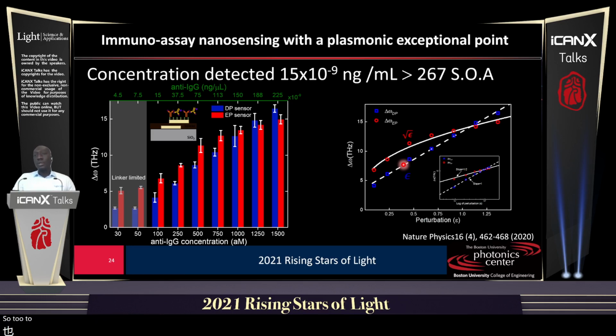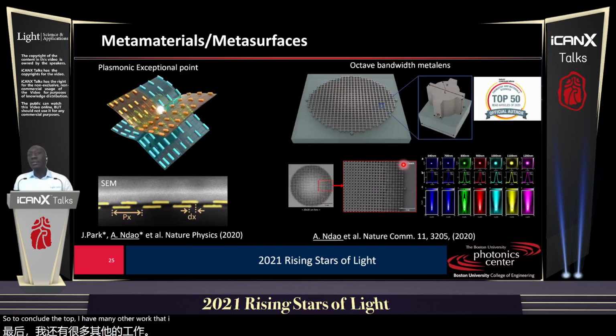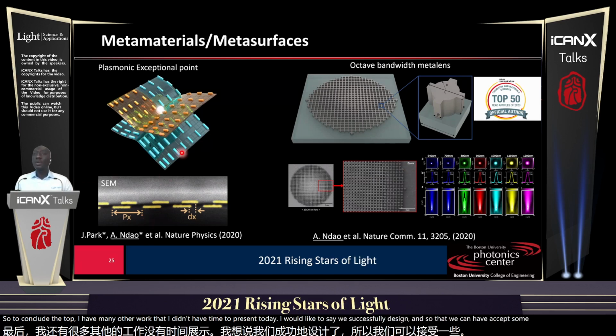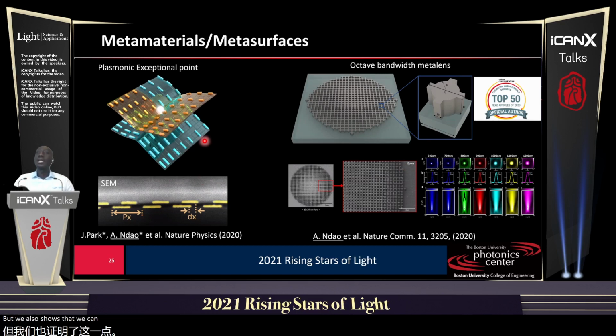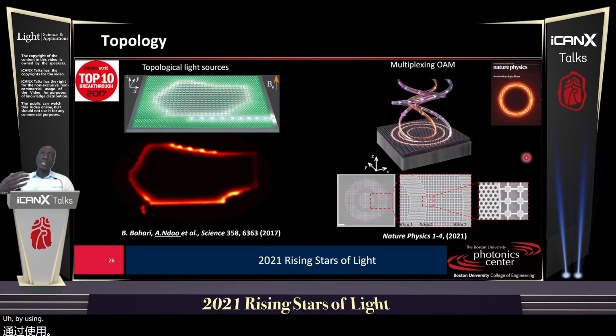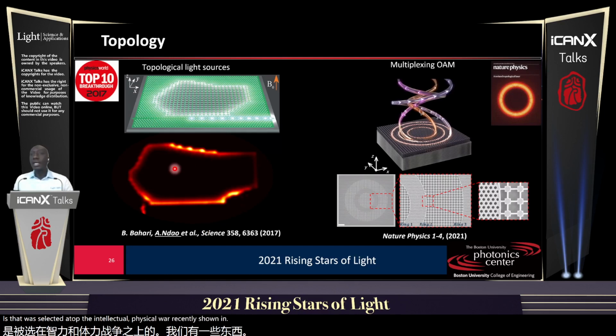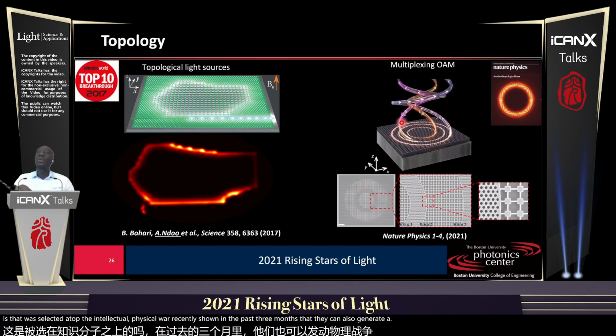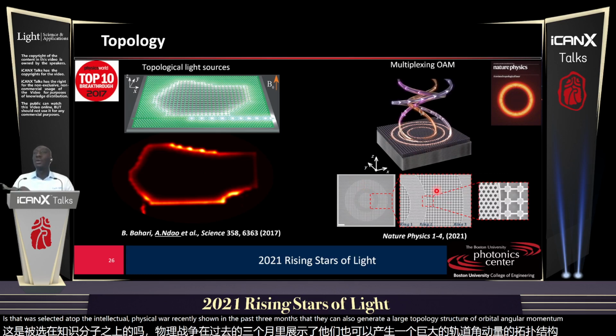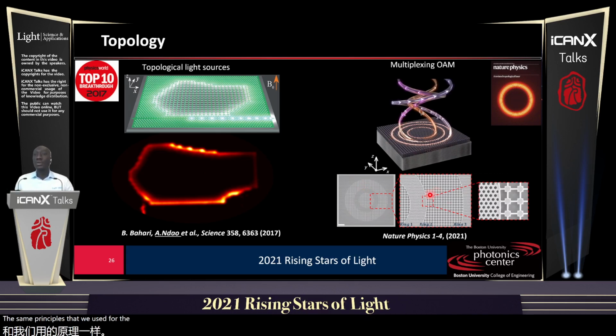So to conclude the talk, I have many other works that I didn't have time to present today. I would like to say we successfully designed and showed that we can have an exceptional point in the plasmonic system, but we also showed that we can have the highest bandwidth metalens using a metasurface with a single layer. And this work was selected as one of the most read papers in Nature Communications. By using the physics of topology also, we showed for the first time a topological laser that was selected as a top 10 breakthrough by Physics World. We recently showed in the last 3 months that we can also generate a large topological charge of orbital angular momentum using topology, the same principle that we use for the topological laser.